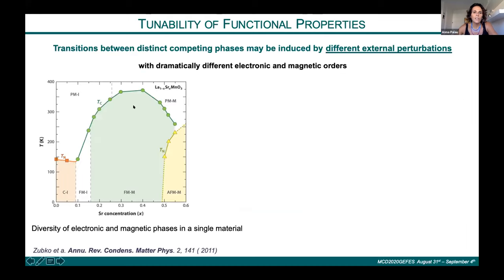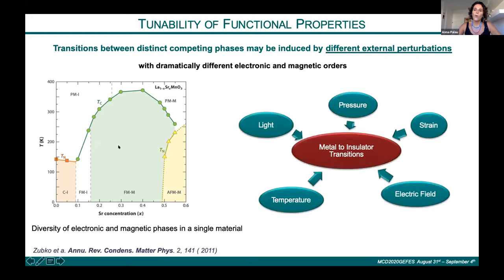In particular, for example, in this figure I show a graph of lanthanum strontium manganite, where we can see that depending on the temperature and the strontium concentration, many different phases showing different electronic and magnetic properties can be found, and the transition between them can be induced by temperature or by concentration. Moreover, many other metal-insulator transitions can be induced in this material, or in other strongly correlated oxides, with external perturbations that may be used to fabricate different devices.